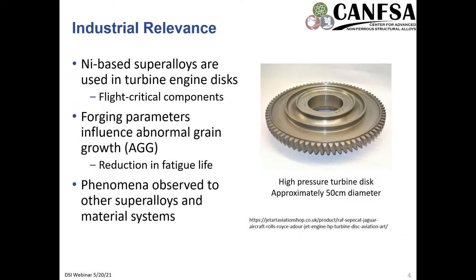And so for the industrial relevance, as I mentioned a little bit, but to go into a little bit more detail, these nickel-based superalloys are used in these turbine engine disc applications. And these are considered flight critical components, meaning that failure of this component through crack propagation can lead to loss of not only the component and the engine, but also the entire aircraft. So reducing the failure of these components is quite important.